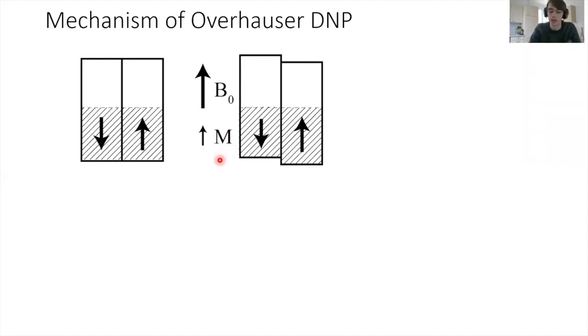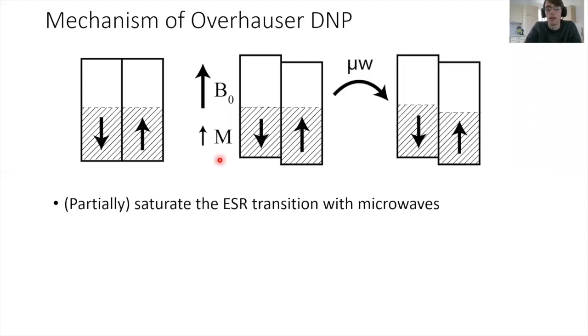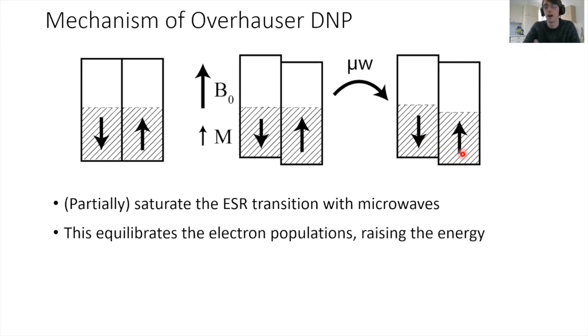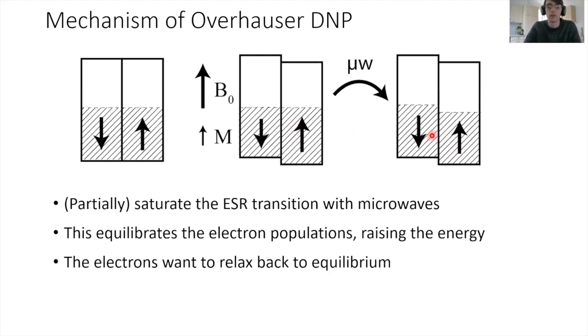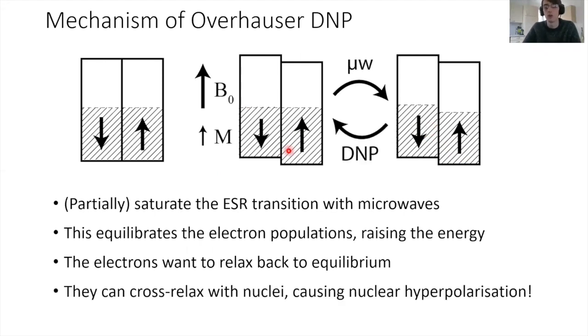So we have an applied moment, induced moment. But in an Overhauser DNP experiment, we then irradiate with microwaves at the electron resonance transition, and this partially saturates the transition, and so we end up, at least partially, with equilibrated populations of our up and down spins. And we can see that this is a higher energy arrangement than this one. We've raised these spins in energy, and they want to relax back to equilibrium. They can do this via cross-relaxing with nuclear spins, and that's what generates our nuclear hyperpolarization. So we irradiate with microwaves, equilibrate the population, and then as it relaxes back, it hyperpolarizes our nuclei.